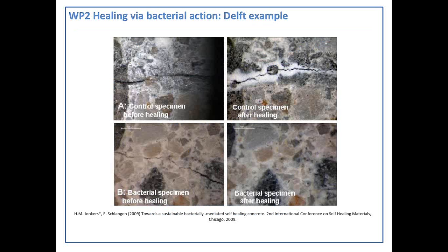So to give you an idea of what this looks like, on the top of this slide, the top two pictures are the natural healing process, which I was talking about earlier. So the white material around the crack on the top right picture is the precipitation of calcium carbonate I was mentioning. On the bottom is a specimen which has had bacteria introduced to it for the same healing process, and you can see that on the bottom right the crack has completely disappeared because it's been completely healed using this bacterial action. This is work that was done at Delft University.